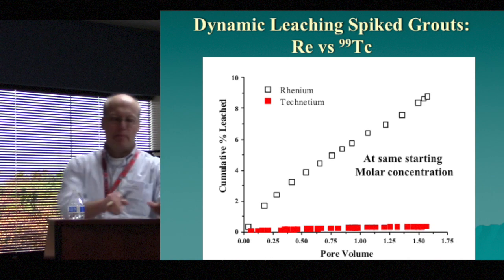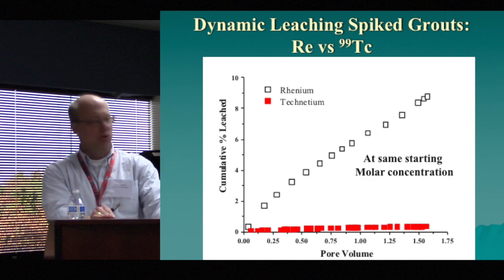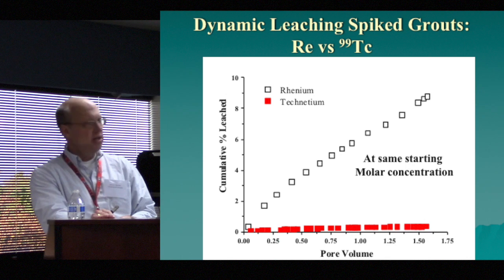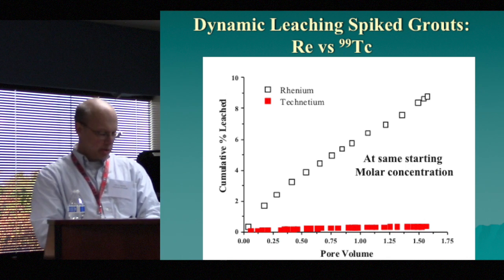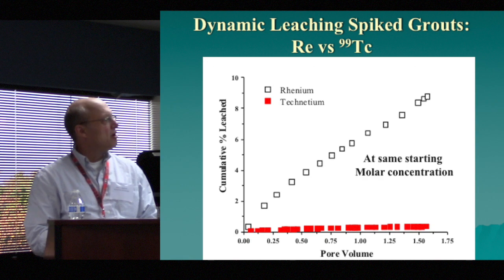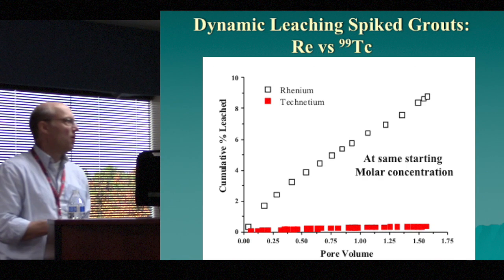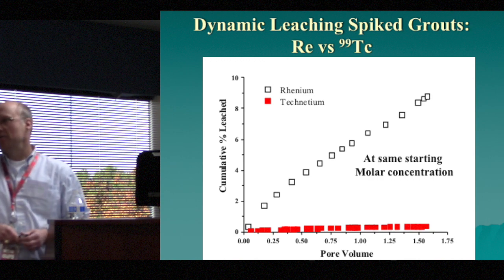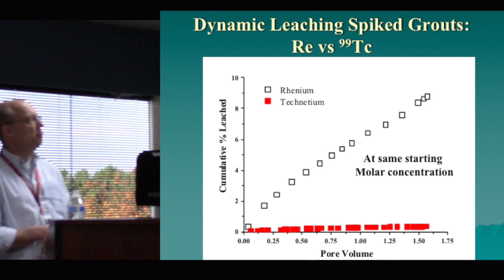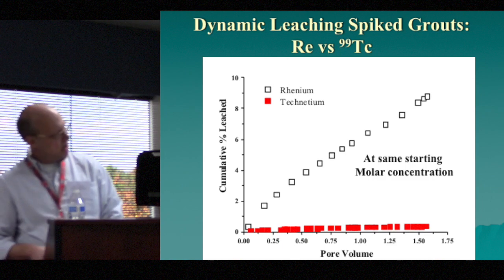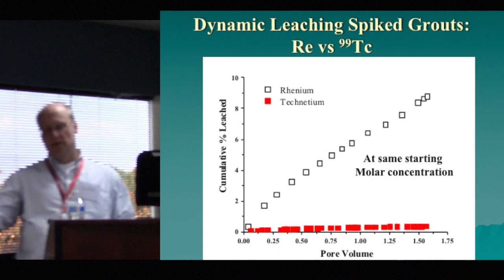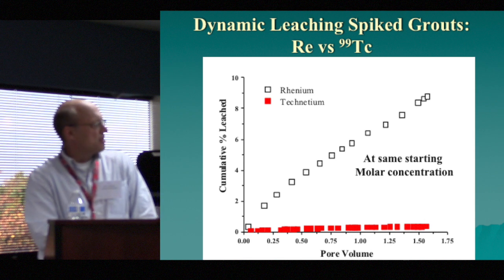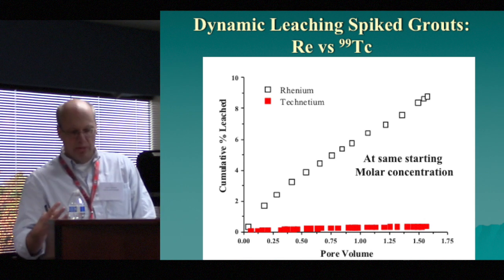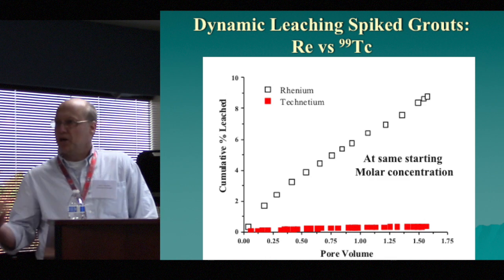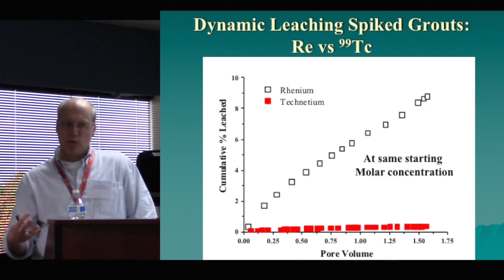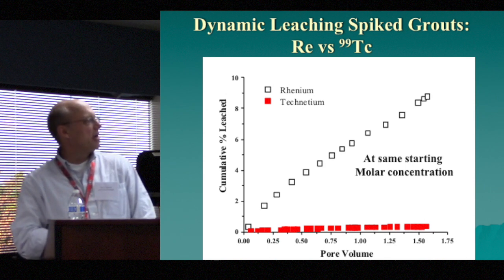So today we did a bunch of samples that were spiked with rhenium. We did one spike sample with technetium, and we also now are doing some SEU samples as well. Consistent with what we saw before, rhenium came out of the sample very, very fast compared to technetium. The other thing that's important to note, and Steve talked about this a little bit, is that I have this on a pore volume basis. That's a little bit arbitrary. It was just a way to compare different samples. And we're working on different ways to try to get a handle on this.